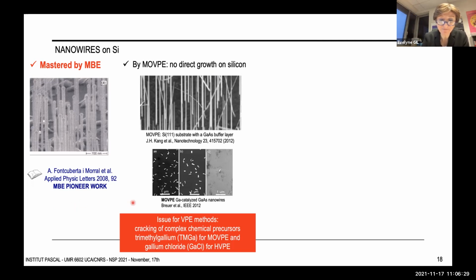But it's not the case for VPE processes, because they use complex chemical precursors, not gallium and arsenic beams directly. And these chemical precursors interact with the silicon substrate, and unfortunately not in the appropriate way. As a matter of fact, MOVPE needs a gallium arsenide buffer layer to circumvent the issue of the melt-back etching of silicon with the organometallic precursors. And if you grow directly on silicon, obviously you have problems with nucleation, as you can see here with the very low density of grown nanowires.